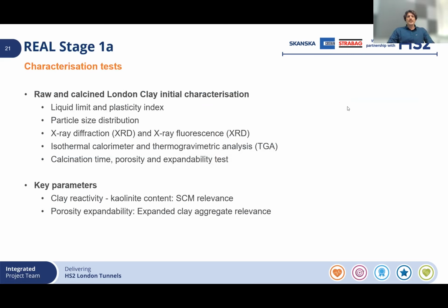That's okay. So in terms of characterization, we had to carry out certain tests to find out more information on the raw and calcined London clay specifics. Raw tests include liquid limit and plasticity index, which are typical tests done in soil characterization, particle size distribution, XRD and XRF. Apologies for the typo there. Isothermal calorimetry and thermogravimetric analysis determine some of the reaction properties, and of course calcination time, which is relevant to calcining the clay for use as a supplementary cementitious material. Porosity and expandability testing shows how it behaves for expanded clay aggregate.